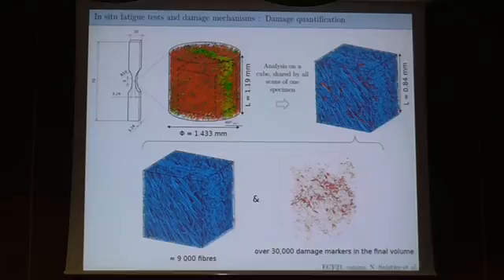What we are interested in also is the damage quantification. So how we do this, we are splitting the microstructure between the fibers, the matrix, and the damage. The damage is a given range of gray levels. So at the end, you can have the fibers and the damage. 9,000 fibers in the image volume, more than 30,000 damage markers. So you have a statistic here, which is quite interesting.